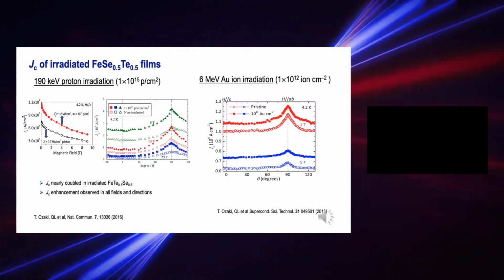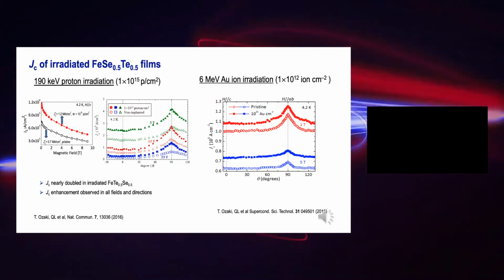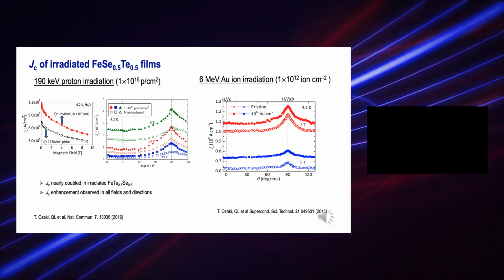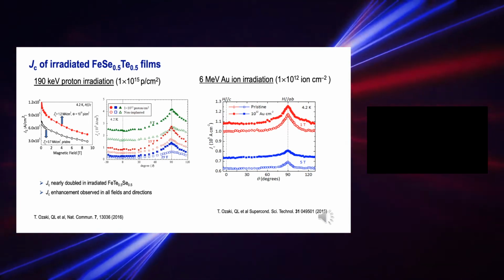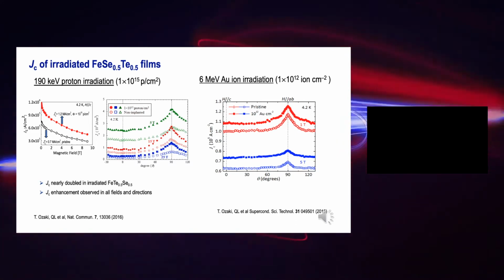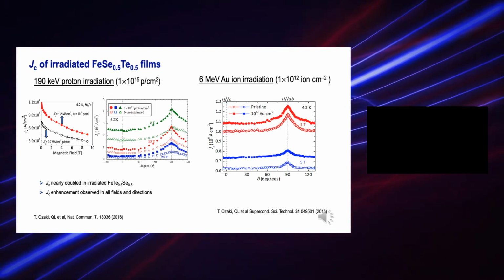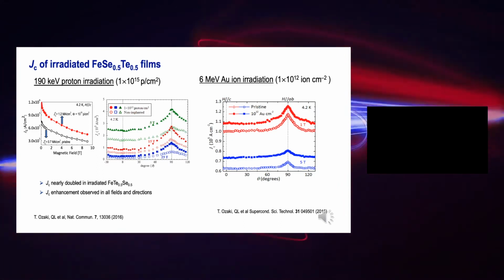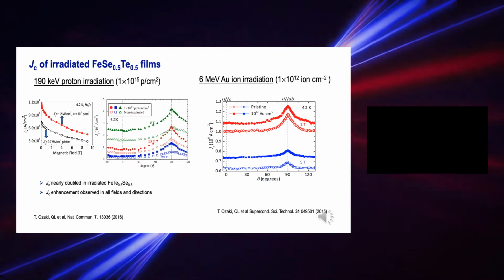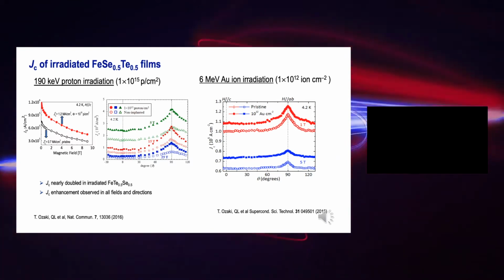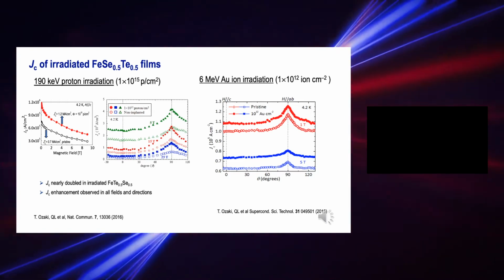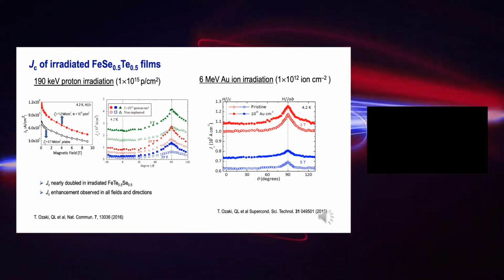Now we found that this low energy proton irradiation not only enhances the TC, but also enhances the JC of the films. Shown on the left-hand side is a figure of JC plotted as a function of field at 4.2 Kelvin. Through the radiations, JC is doubled. Now, this JC enhancement was also observed in all fields and directions. This is shown in the figure in the middle of this slide. The JC is plotted as a function of the angles, and the data were taken at 4.2 Kelvin in magnetic fields as high as 25 Tesla. Solid symbols are the irradiated ones, and open symbols are non-irradiated. As you can see, overall JC is enhanced in all directions and fields.